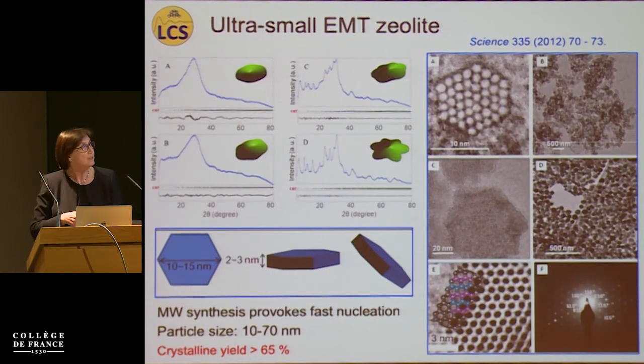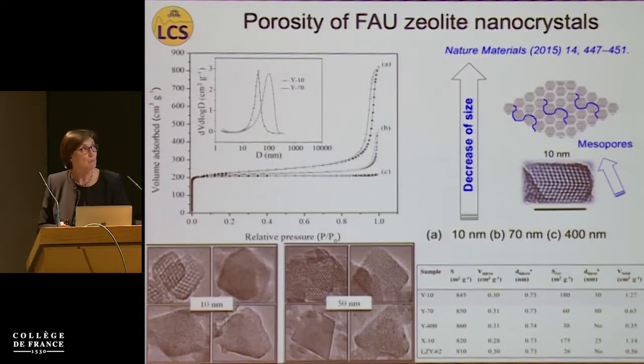Under high-resolution TEM, these particles appear as perfect hexagonal crystals. The size is around 10 to 15 nanometers, and the thickness is around 2 to 3 nanometers. By replacing the conventional heating with microwave irradiation, we were also able to increase the size of the crystals up to 70 nanometers, but also we substantially increased the crystalline yield, which is above 65%.